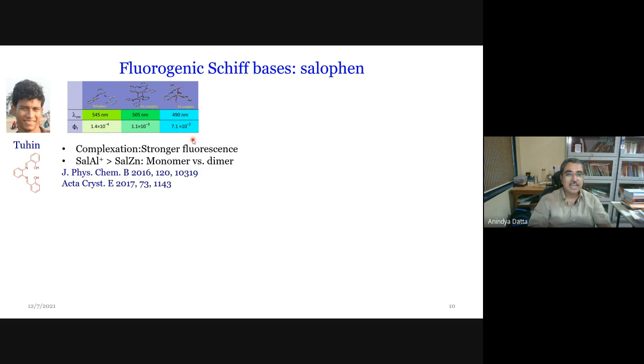That is the question we had, and the answer seemed to be that the aluminum complex is a monomer. The zinc complex is a dimer, and a pi stack dimer. So the two salophen moieties come very close to each other. So a lot of things can happen between them. You can have X-dimer formation. You can have a host of other processes. We do not really know exactly what processes happen there. But the experimental result we have is that when it is dimeric, it is not as fluorescent as when it is monomeric. But then we wanted to test this hypothesis.